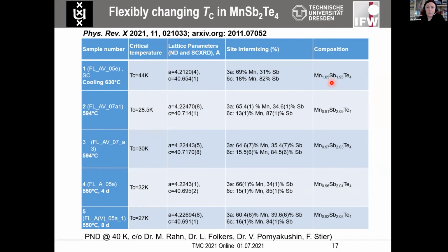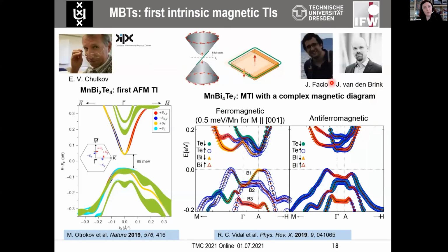So while it will take quite some time to study this matrix and make some sense out of it, it would be very interesting to see more calculations done on the disordered models, which of course very quickly become a very large superstructure if you really want to look at disorders of 5 to 10%. Here I'm not showing any details from my group in cooperation with theoreticians or other groups of theoreticians working on these disordered models. This is still quite ongoing, but I want to show you that in fact this family, already with the idealized compositions, was found to be very flexible.